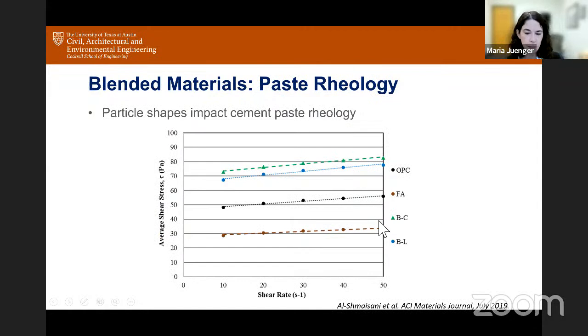What happens in this case, which is not surprising at all, is if you look at these particular materials in rheology testing, where you're looking at the slope of the line as an indication of viscosity, and the y-intercept as an indication of yield stress, you can see that, with an OPC, you expect that a fly ash will have a lower yield stress because of the rounded particles. And what you see is that if you mix a fly ash with a natural pozzolan, you remove that beautiful effect of the spherical particles by mixing it with an angular material, and you actually increase the yield stress of the materials.